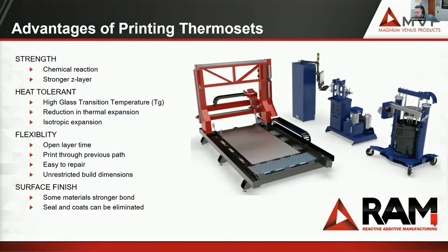It's going to be about the open layer time that you have, because we're printing at room temperature. We're not heating this material up, and we're not having a heated table or a blowing agent on it. It's all being done at room temperature, and these materials are meter mixing together at the gun head and deposited out. When they actually cure, the gel times can range from 15 minutes to 30 minutes. It builds that stability, and we're stacking off of those beads. So some of the advantages of printing thermosets is, again, the chemical reaction between the two different materials is actually building a much stronger Z layer strength than you typically see in thermoplastics today.